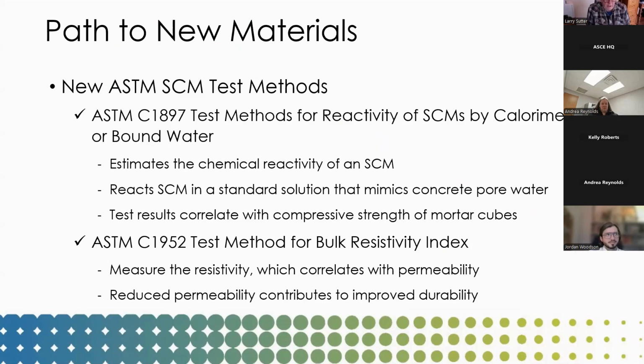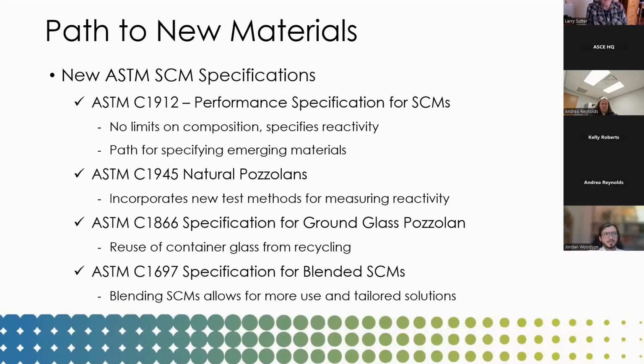And then an even more recent test is C1952, which has just been recently adopted, which measures the bulk resistivity, which again correlates with compressive strength, but more importantly, correlates with durability. As we reduce that permeability, we improve the durability. So this C1952 is a new way to assess the impacts or contributions of an SCM where we've never been able to do this before. Next slide. In terms of new specifications, we have C1912, which has just recently been published.